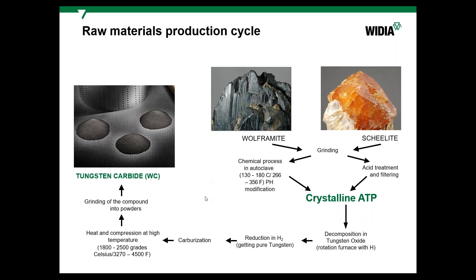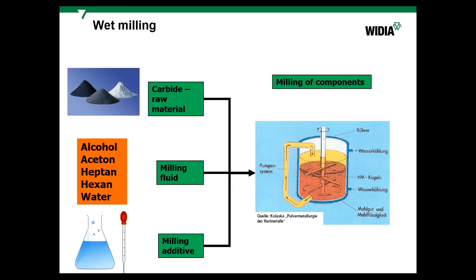The tungsten carbide must be united with cobalt and other additions such as chromium carbide. Wax or polyethylene glycol is also added — this acts as a temporary glue to keep the pressed shape intact. All ingredients are mixed together in a drum with spirit or water, and carbide rods, balls, or small shafts inside the drum rotate to mill and mix all ingredients thoroughly.